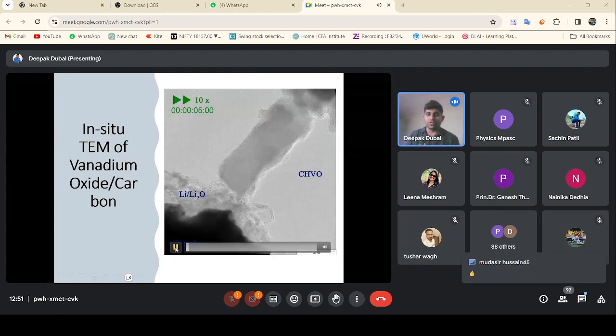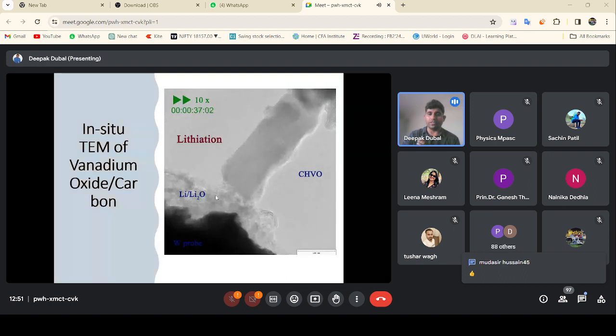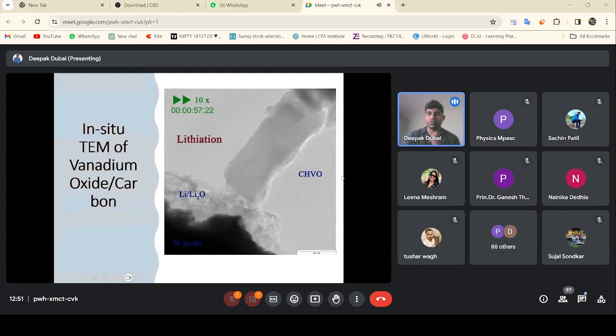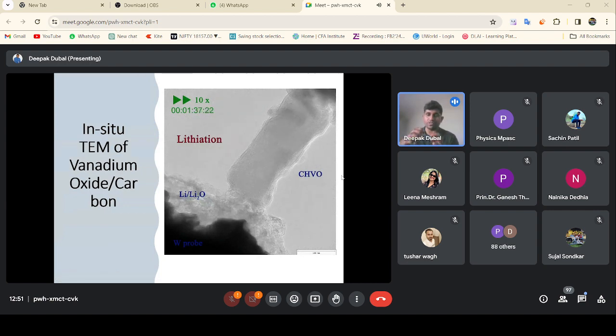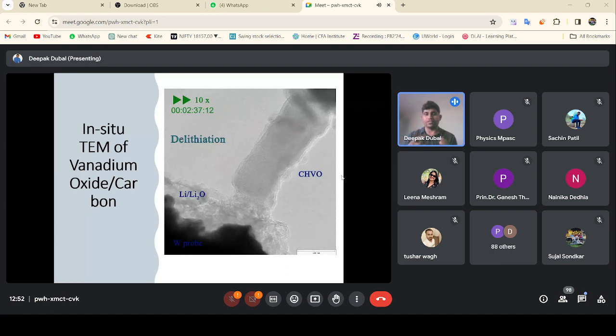So you can see here, we recently did this analysis. This is our material. When we start to charge the material, the lithiation process, it starts to expand. And when we start to discharge, it starts to contract. And this is what we are actually seeing in the transmission electron microscopy.